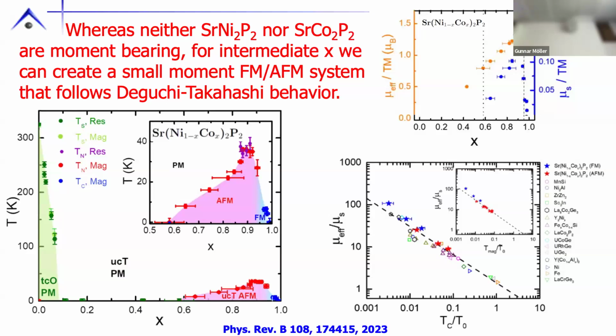Now, someone should call me out on my statement about ARPES, because a lot of this is under pressure and you can't do ARPES under pressure. Now, we've been able to finesse it by annealing and playing around, so that we can get both uncollapsed and collapsed in the calcium, and we can look at that in ambient.